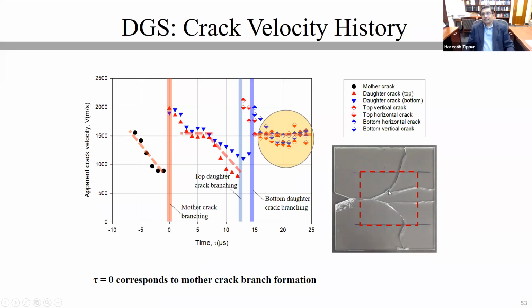Notice that each of these daughter cracks branched once more. So as a result, you see the two blue lines. These two blue lines in an ideal experiment should be coinciding on top of each other. In this case, the upper crack branched a little bit earlier than the lower crack, and those are about 2 to 3 microseconds apart from each other. And once the branching took place, the four daughter cracks branched, there are four different sets of symbols over here, shown by these diamonds. And they all settle down to the 1500 meters per second here. So once again, as I had noted multiple times, slowing down of the crack is a clear indicator that the crack is about to branch. These are macro scale velocity measurements. And that happens in each of these three branching events that we have seen in this larger specimen.